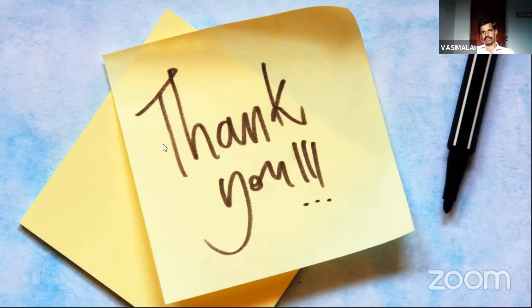I did not touch on the graphene based material at all, because I don't claim to be a nanochemistry man, right? I do work on the material, but your question is valid. Many people are working on that one. They quote, we also have done a lot of work, but the stability issue comes into picture. As long as you grow the graphene by CVD method, that will go well. By simply converting your graphite to graphene oxide and converting back to graphene, what we call the reduced graphene oxide, and depositing on the copper foil, may not have a long cycling life. That is my major concern.